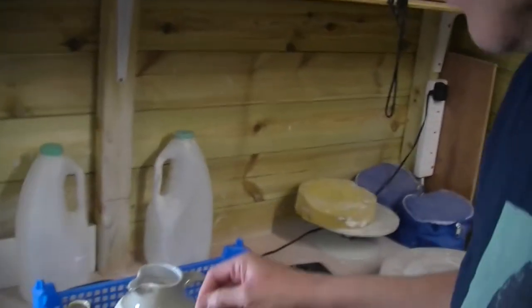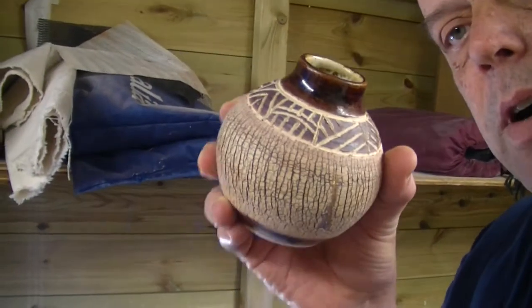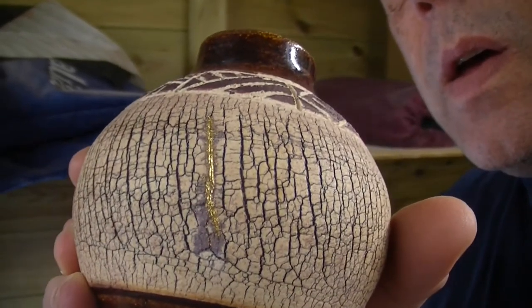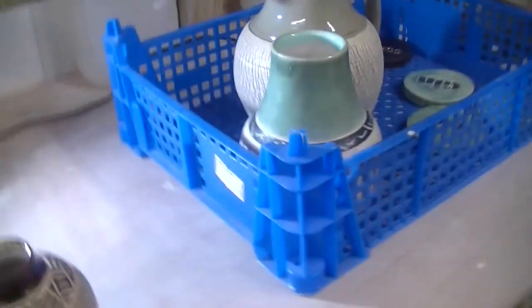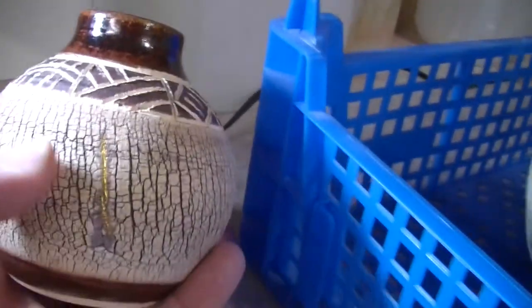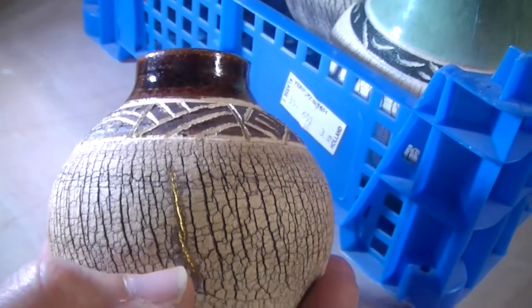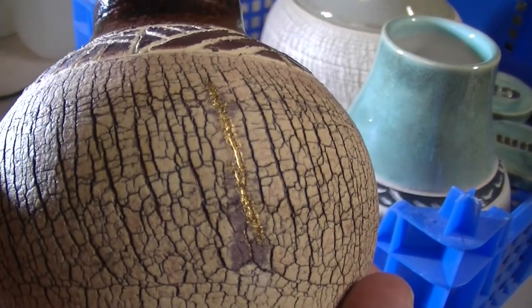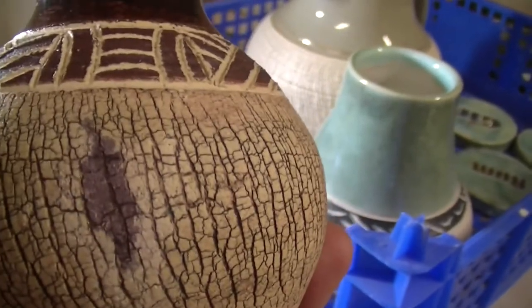Okay, update for our lustre — it's been a while in real terms but we have some results at last, which are over here. Mixed results, shall we say. So we did this little bar — you can see on there that's the gold lustre. The gold is a bit purple now; that's what happens when it goes a bit thin. I'm going to attempt to Dremel that off. I've got one on the other side which is worse — the lustre didn't take at all on that bit, it's just purple — so I'm going to try and Dremel that out.